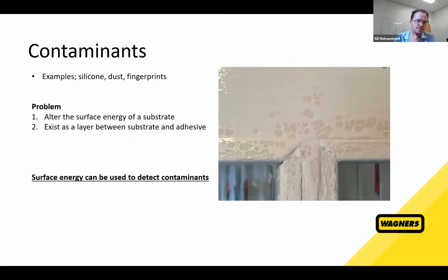The other aspect of a good bond, aside from the surface energy of the surface, is the presence of any contaminants on the surface before you bond. So contaminants can take the form of dust or fingerprints. A big one is obviously silicone contamination. Silicon is quite often banned in a lot of industries, aerospace, et cetera, where they do critical and large scale bonding because it is such a bad industrial contaminant. Even a tiny amount of silicone on the surface can affect your bond quite significantly. On the right there, you can see very, very bad silicone contamination on a surface that has been painted, and you can see it beading up, showing how the paint is not wetting out that surface and coating it because of that contamination.